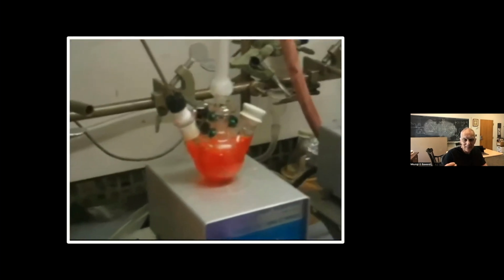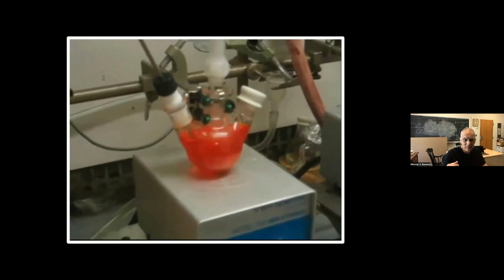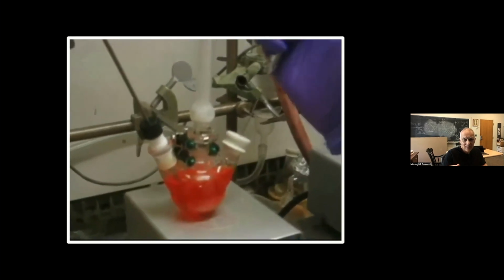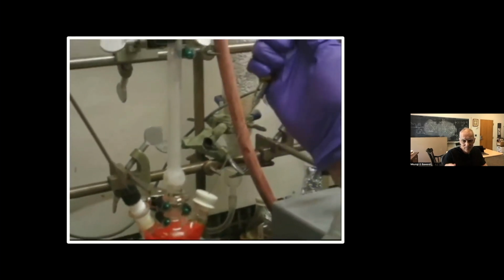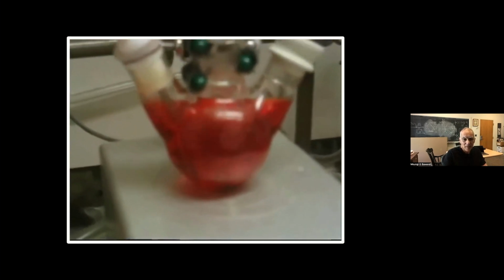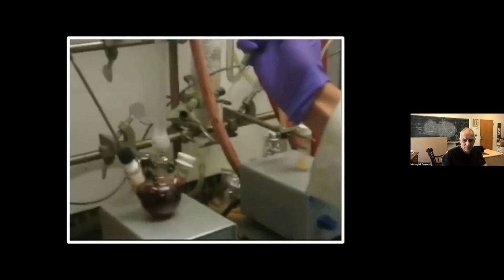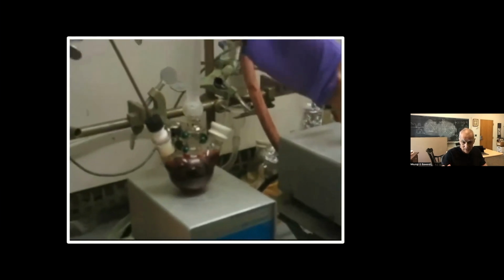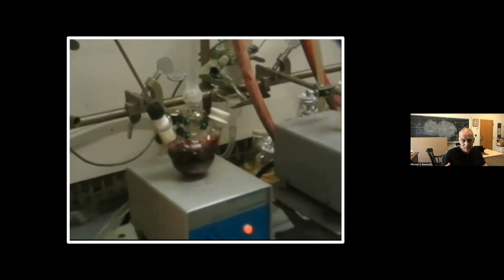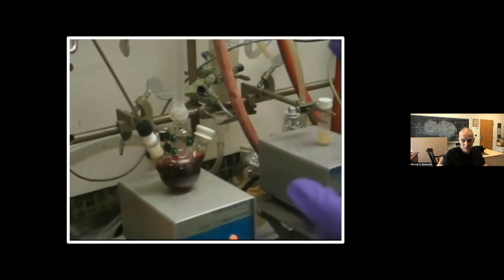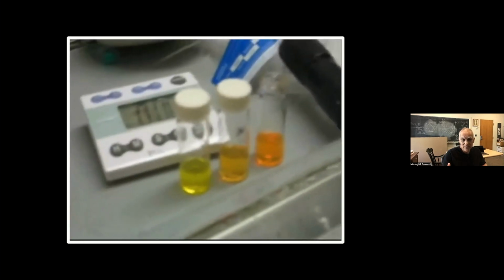Those are the little seeds of cadmium selenide. They're about 2 or 3 nanometers in size that form. He's taking samples out to show us what's happening as the particles then grow in there. And I'll spare you the 20 minutes of growth. And here now it's much deeper color, so the particles are bigger. The wavelength of the electrons is larger in these particles. Then you can see the series of color changing.